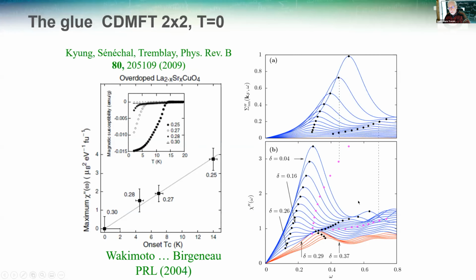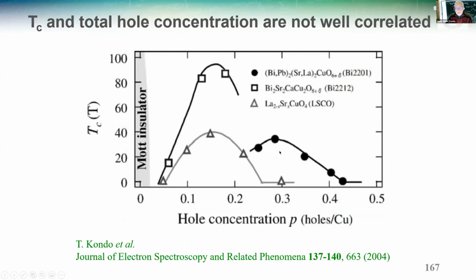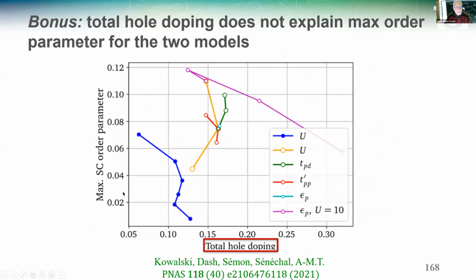I can tell you more about retardation a little bit later, but the message I want to give here is that the simple mean field picture we had at the beginning with J is not quite correct. There is retardation. We get two bonus results. One of them is that in the experiment, TC and the total hole concentration are not well correlated. You see the optimal TC here is for 0.3 doping, and here the optimal doping is around 0.15 doping. And indeed, if we calculate the value of the maximum superconducting order parameter for all these different models as a function of total hole doping, you see there's no correlation.